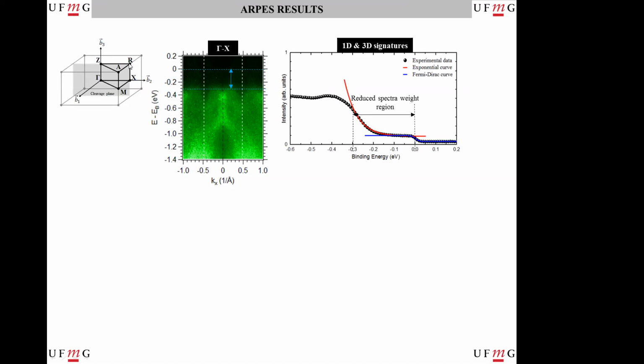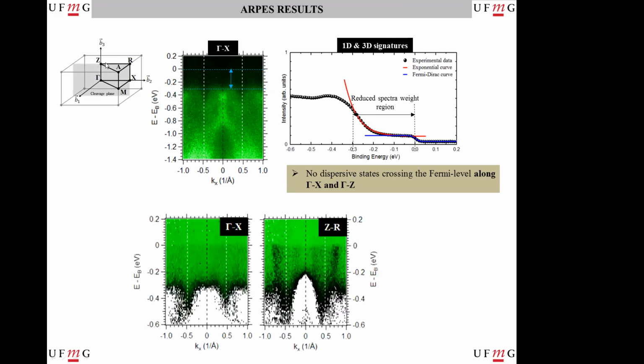We went to the ZR direction here, and like the other results, we didn't see states crossing the Fermi level. But when we went to this direction here, we can see that there are dispersive states crossing the Fermi level. And these dispersive states look very similar to the Dirac cones of the topological insulators, which connects the two results that differed from the previous results.